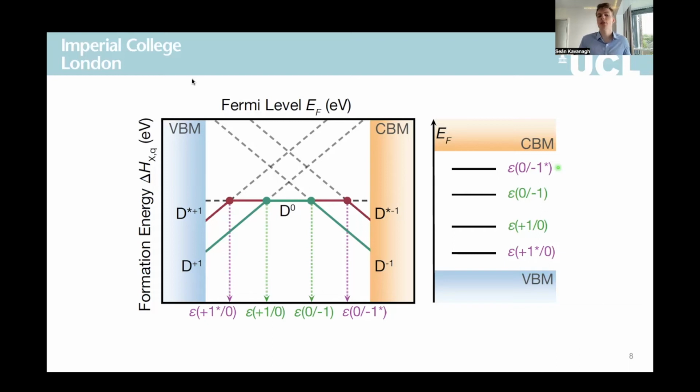So while this conventional wisdom does hold in many cases, particularly for defects in conventional semiconductors and ionic materials like oxides, where the defects themselves are high symmetry, exhibit harmonic potential energy surfaces, and don't distort much between different charge states. This behavior often does not hold, however, for many emerging inorganic materials which exhibit anharmonicity and significant structural distortion between defect charge states.